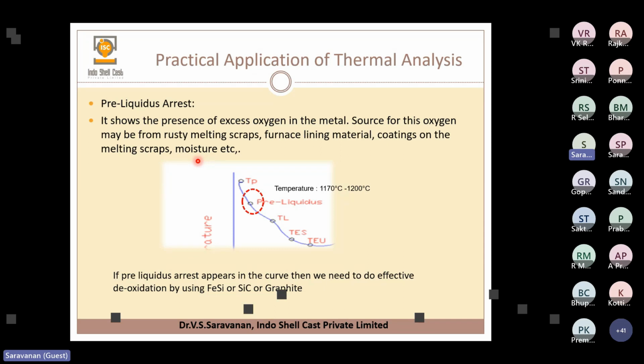comes from rusty melting scrap, furnace lining, coatings, and moisture somewhere. So if an excess amount of oxygen is there, the cooling curve will show this small pre-liquidus arrest point. So sometimes if we have the pre-liquidus arrest point, it shows a larger amount of oxygen, so we have to remove the oxygen by adding deoxidizers. So this is one important thing. Excess oxygen is not desirable.